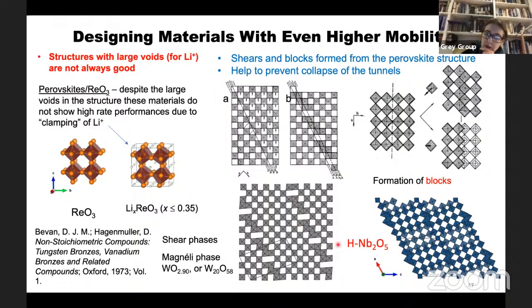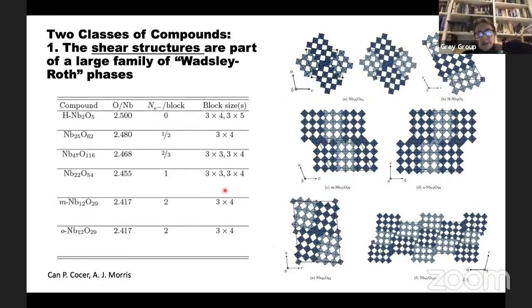stability to the structure. And in a niobium oxide, in order to compensate the missing oxygen, you actually have to shear in multiple directions to get blocks. And so this is an example of a whole variety of different niobium oxides, where depending on the ratio of oxygen to niobium, you can get different block sizes, and they have different electronic structures.